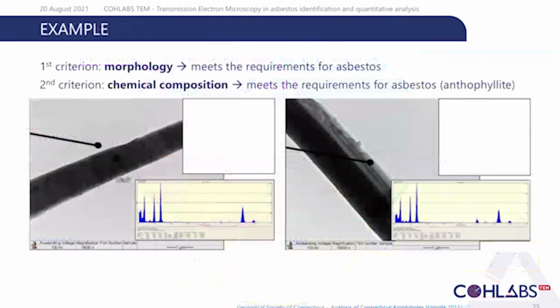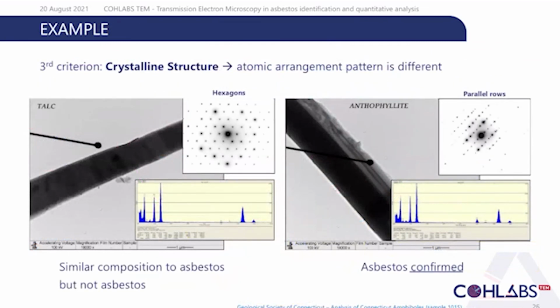So this is an example to show the importance of the third criteria, because if we are looking only at the morphology and the chemical composition between those two pictures, you would think that these two fibers are similar. And if you compare the chemical composition to your references, you might think that these two fibers are indeed anthophyllites. But to have an unequivocal identification, you need to look at the crystalline structure, and that's where you can get surprised sometimes.